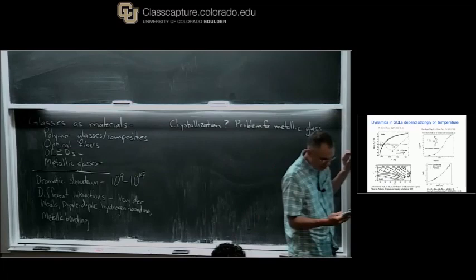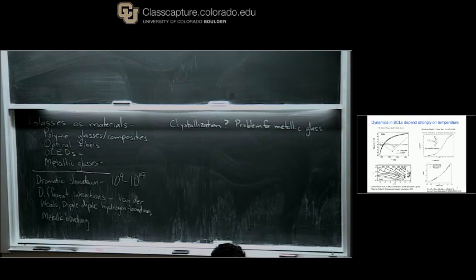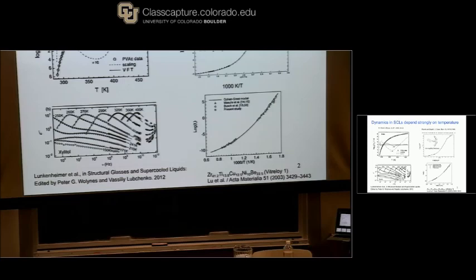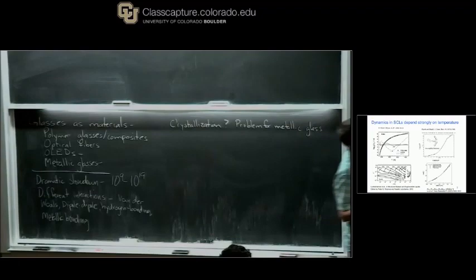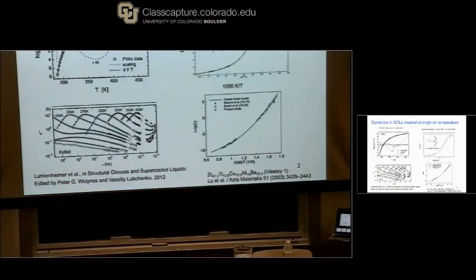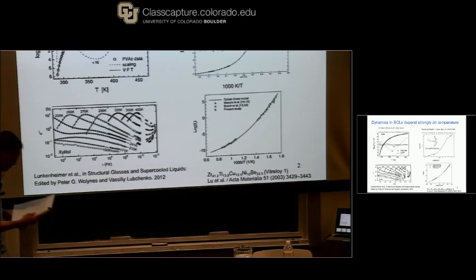It's worth saying just a bit about how the other systems managed to avoid crystallization. This polymer is called an atactic polymer — it has random stereochemistry along the backbone, which means that it's basically impossible to imagine how it would fit into a crystal. Another way to think about this is that it's an extremely complex mixture — many, many different components that have different stereochemistry.